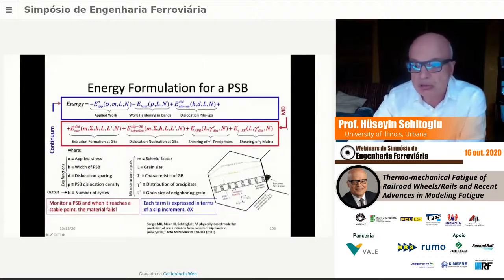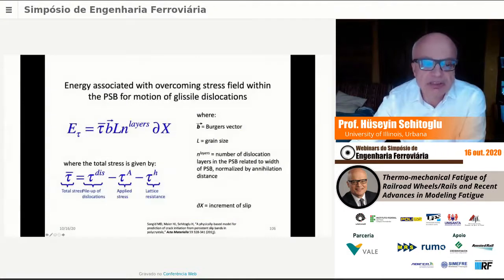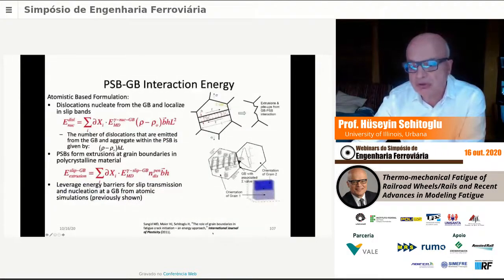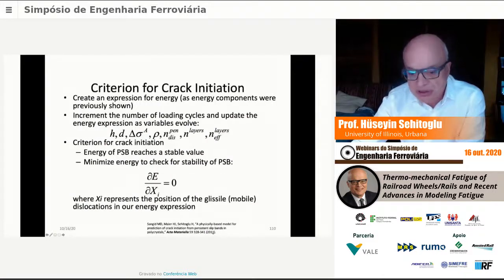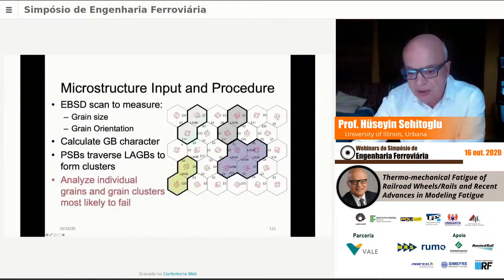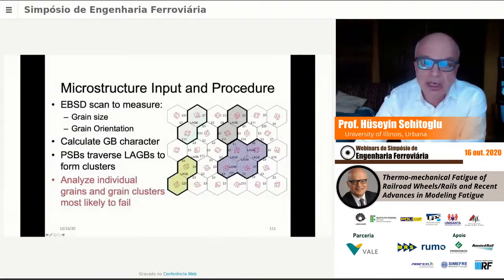And then we go back to our persistent slip band, and we develop an energy model with the continuum terms and the non-continuum terms. We say molecular dynamics here, but these are energy barriers that are obtained. But the formulation is running on a desktop computer once we have everything. And then we look for the minimal of this energy to get the condition for onset of fatigue crack nucleation. And this is also outlined in this paper. So this is 2011, roughly. I don't want to go into the details of this. They are in the paper.